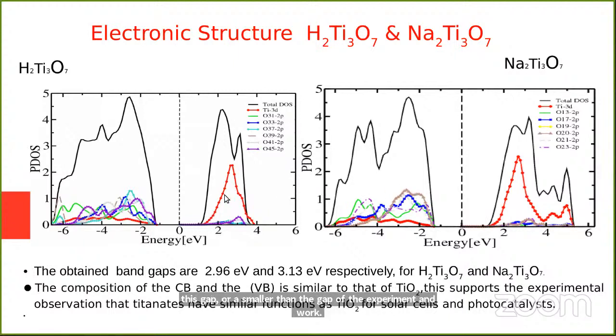But they are in the same range as titania. And from those two structures, we can see that the titanium 3d states are dominant at the bottom of the conduction band, and the contributions of hydrogen and sodium are negligible. The composition of the conduction band and valence band is similar to that of titania. This supports the experimental observation that the titanates have a similar function to titania for solar cells and